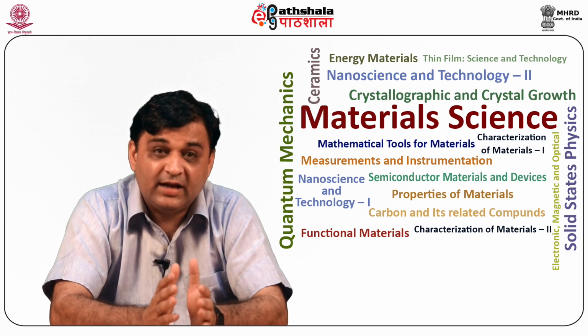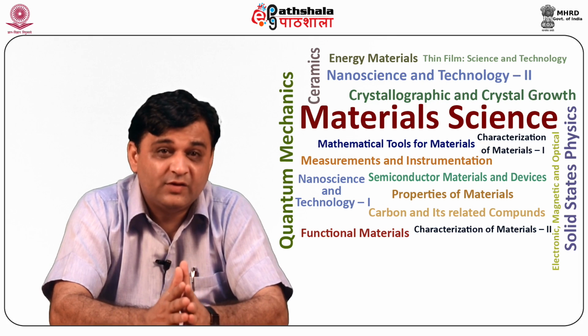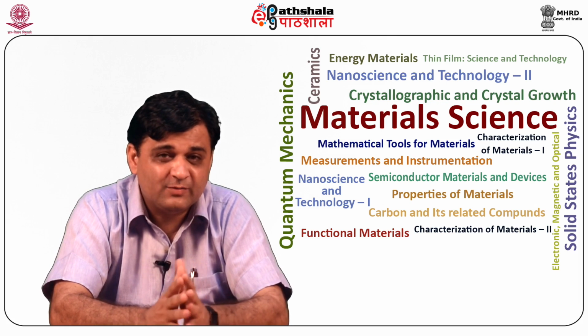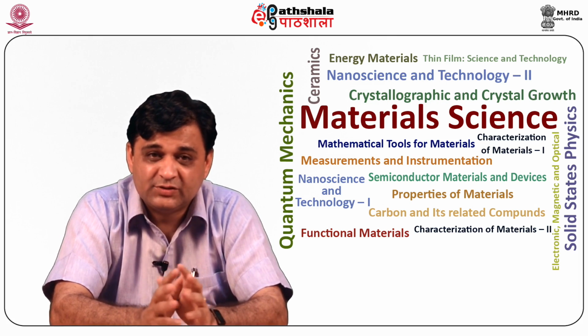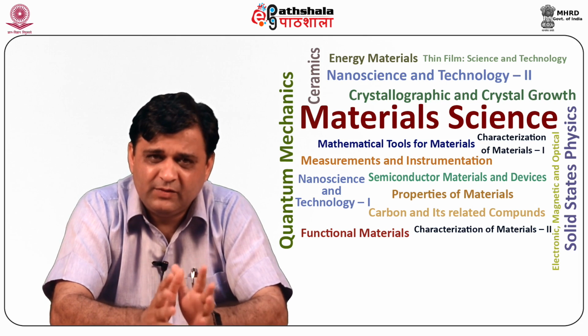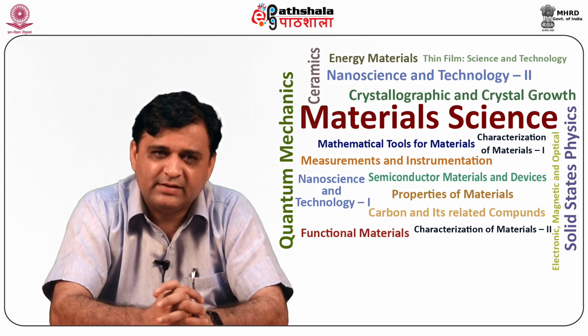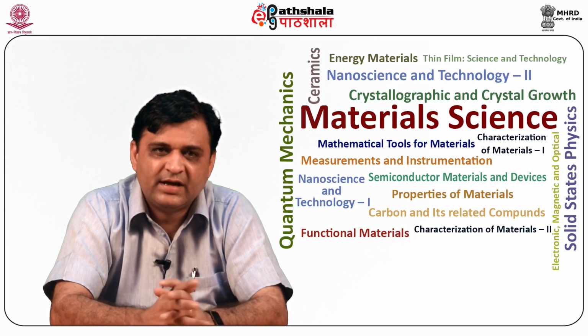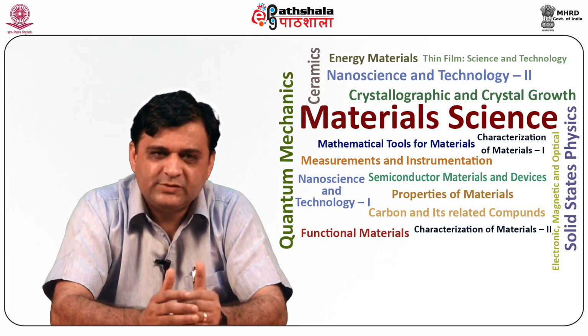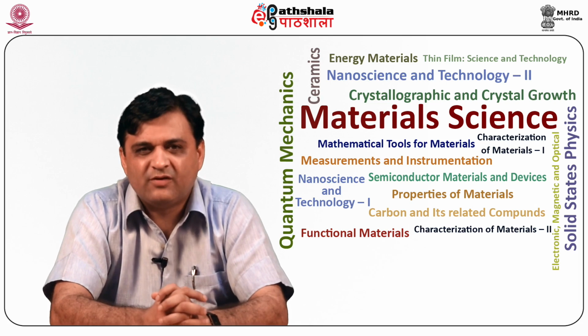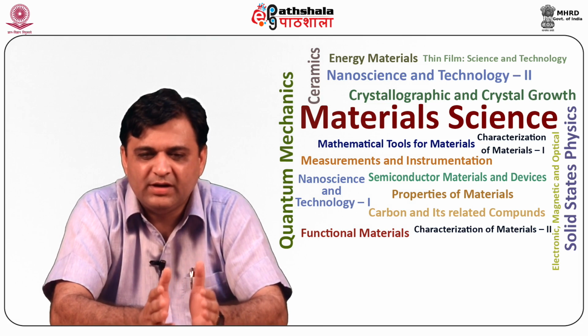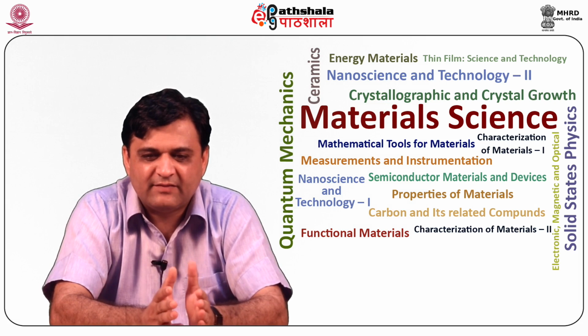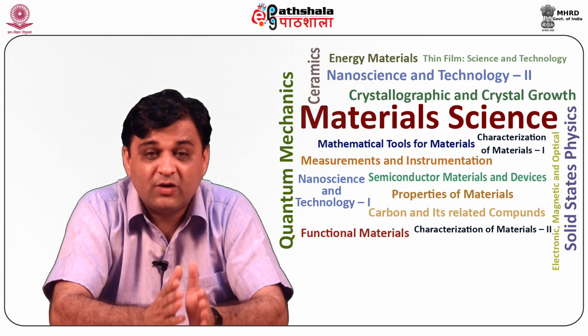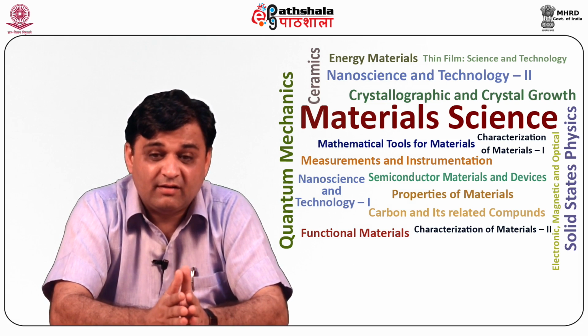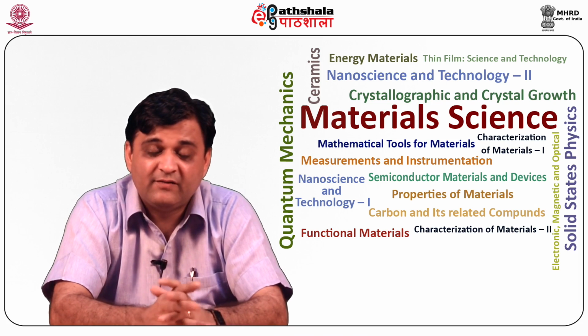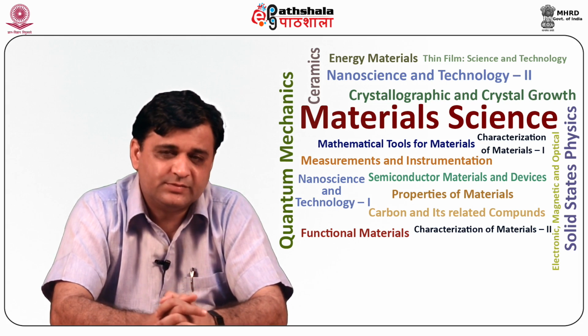The alignment of the sample is also very crucial here, because we are dealing with very small angles and very small thicknesses. If there is a slight misalignment, we don't observe a good reflectivity, and the analysis suffers. Also, sufficient electron density contrast is required between two media. When we have several multilayers, if there is not sufficient electron density contrast, the reflectivity will not come out well.